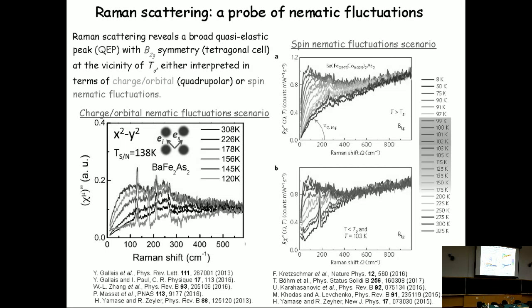And then I come to Raman scattering, which is actually the main technique that I'm going to show here. It's been shown by several works that Raman scattering is sensitive to nematic fluctuations. So we have inelastic light scattering that can lose or gain energy when interacting with these fluctuations, which, as I mentioned, could be charge fluctuations or spin fluctuations. They are coupled together. And there are mechanisms that have been proposed to explain the Raman signal, either considering that they come from the charge or orbital nematic fluctuations, or from spin nematic fluctuations. As I mentioned, both of them are there. And the question is, which are giving the Raman signal?